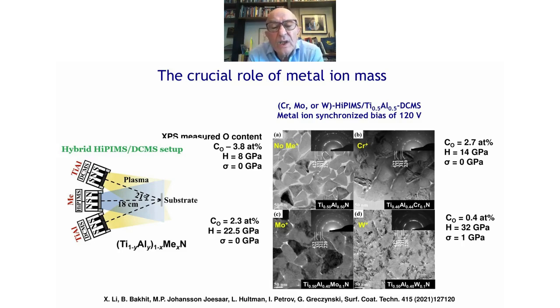When we go to chromium, this is oxygen which is absorbed into these voids after deposition. We get densification, reduced oxygen content, increase in hardness, a little bit more for moly. But when we go to tungsten, you see the oxygen content is below 1%, and this is probably due to the background pressure during deposition, which we cannot avoid, and the hardness is highest, and the stresses are relatively modest. Next slide.